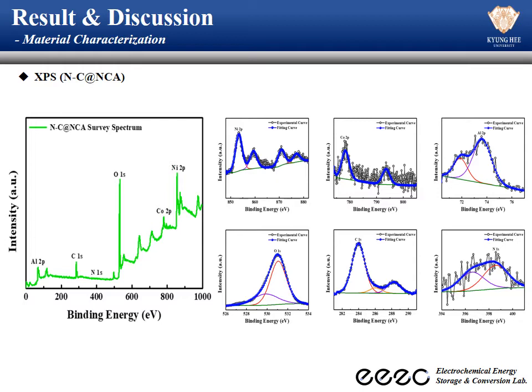And despite the formation of the coating layer, the nickel, cobalt, aluminum, and oxide peaks do not change. So the nitrogen-doped carbon coating layer does not significantly affect the composition of NCA. In addition, the two peaks appearing in the nitrogen peak are pyridinic nitrogen and graphitic nitrogen, respectively, from the left. And between them, pyridinic nitrogen has an advantage in improving the electrochemical performance of the active material. Therefore, it can be said that the electrochemical performance of N-C@NCA, in which pyridinic nitrogen is formed, has improved.